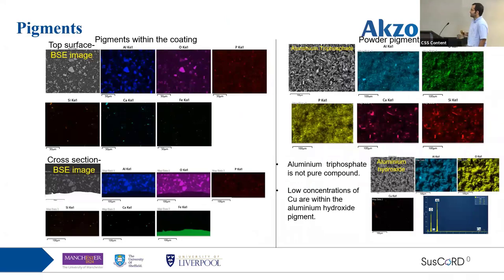So let's start with the pigments that were incorporated into the coating. On the left, you can see the SEM images from the coating showing the pigment distributions, the top surface and the cross section. As is evident, we had aluminium hydroxide particles in the coating, and the EDS elemental maps show the presence of aluminium and oxygen. So these are the aluminium hydroxide particles within the coating. And we had aluminium triphosphate. The phosphorus element shows where the inhibitor pigments are located within these coatings. But other than these, we also had calcium and silicon detected within this coating. So we didn't know the actual source of these pigments.